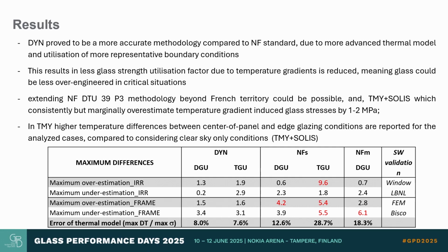So from a general point of view, these dynamic methods prove to be more accurate compared to the NF standard due to the thermal model, but also the representativeness of boundary condition, and this results in a lower glass strength utilization factor due to temperature stress, meaning that the glass doesn't need to be over-engineered in critical situations.